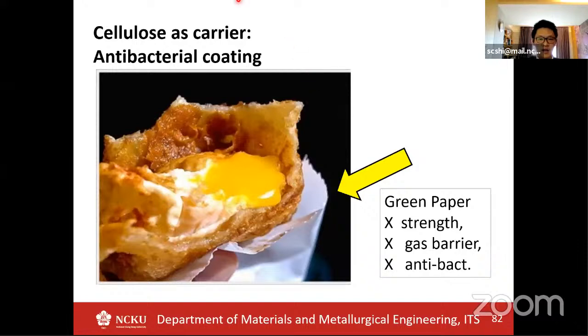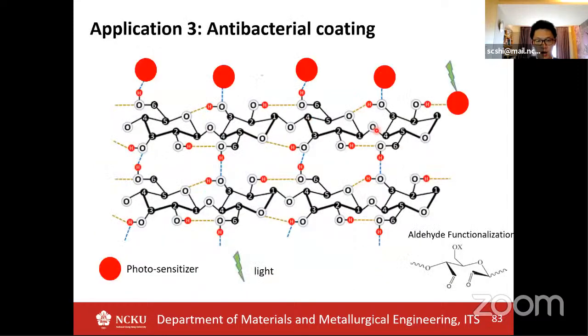And the third example is cellulose as a carrier. Here we use the CNC as an antibacterial coating. This paper bag, we normally use to protect food. But actually this paper does not have enough strength, gas barrier, or antibacterial property. So we use cellulose as a template to modify the functional group of the surface. Here, we add a photosensitizer onto the CNC surface. After shining light, this photosensitizer will generate some ROS. These ROS will kill the bacteria.